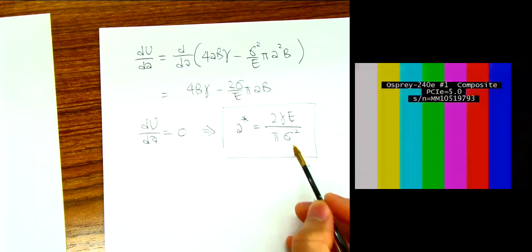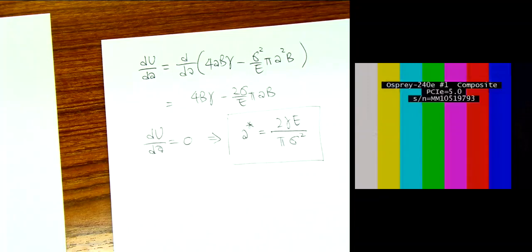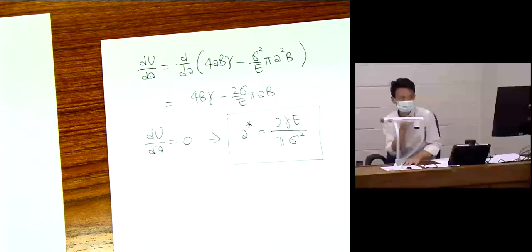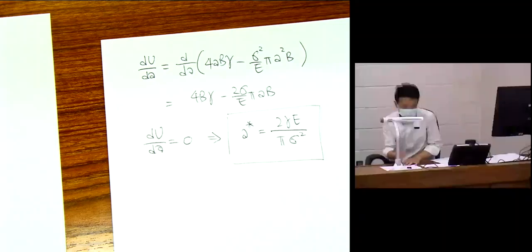Now, obviously, stress can be changing, right? So another way of looking at this equation or formula is to think about things in reverse, because there are two variables here, right? Sigma and A are varying in many situations. We can apply different stresses, we can have cracks that are different sizes, but E and gamma are constants, material properties, right?